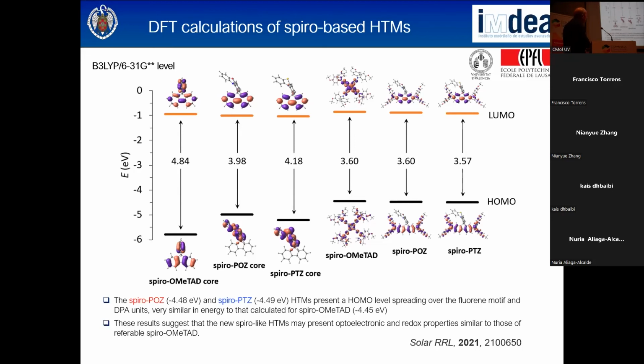But when you introduce the arylamino groups, the situation changes in these compounds, because now the HOMO is mostly localized, similarly to the spiro, on the fluorene, but also on the electron donor units. So it's delocalized over this whole moiety. And the LUMO is mostly maintained over there, more or less. But look at this, the band gap for our 2 new molecules is pretty much the same as that of the spiro. So this is one of the first things in common.